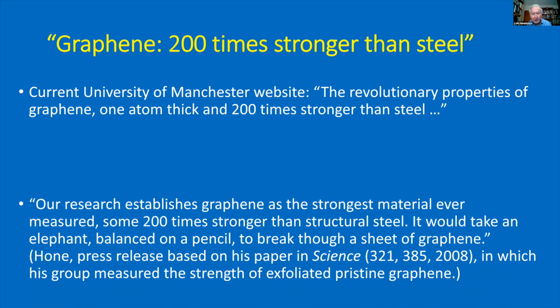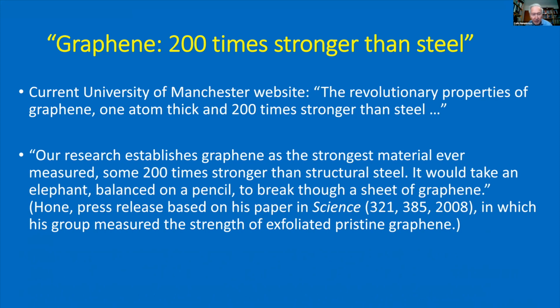And this is another quotation from Professor Hone, something he said in a press release based on a paper he published in Science in 2008, in which his group measured the strength of exfoliated pristine graphene. But then in the press release, he apparently extrapolates their measurement, because he says, our research establishes graphene as the strongest material ever measured, some 200 times stronger than structural steel. It would take an elephant balanced on a pencil to break through a sheet of graphene. So it gives the impression that large area graphene is still 200 times stronger than structural steel.